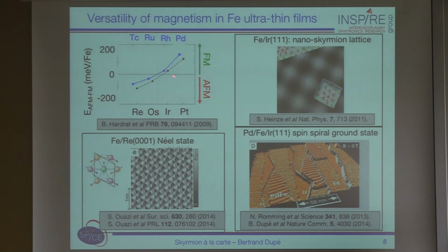And actually, if you take iron on iridium 111, that was published in 2011, this is a nanoskyrmion lattice, which is shown here. So here the spins are rotating very fast. It's stabilized by even higher order exchange interaction, and this is a very, very complex spin texture.